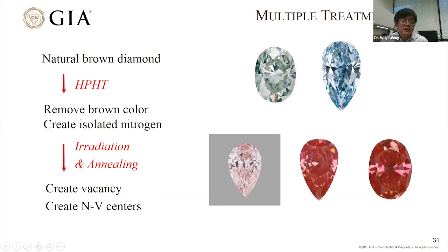Now we know if isolated nitrogen is introduced with suitable concentration. I try to emphasize how important it is with a suitable concentration of isolated nitrogen. If this stone is irradiated and annealed, NV center will be introduced, and depending on the NV center concentration, a diamond could be lightly colored pink. I mean, pink is very popular in the trade, or the stone could turn to red color.